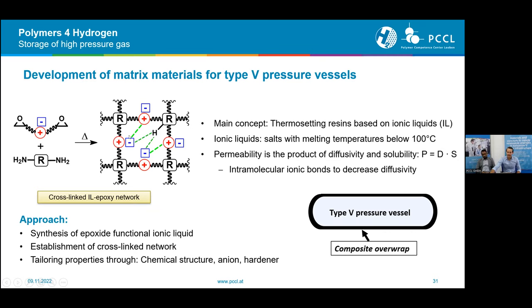The idea behind those ionic groups for us is that the permeability is the product of the diffusivity and the solubility. And we're expecting some additional intermolecular bonds due to those ionic groups, so between those ions and also maybe for hydrogen bonding. Here you can see a schematic depiction of the idea.